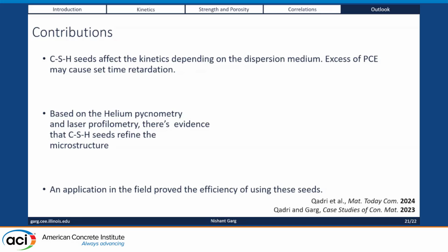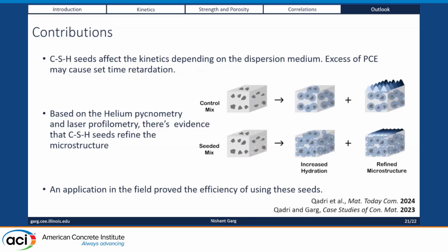Based on helium pycnometry and laser profilometry, there is evidence that we have this microstructure refinement, which is good from a durability point of view. So we refine this picture: you have increased hydration, but also the microstructure is refined. Finally, this is now implemented in the field and is fully documented as part of a report.